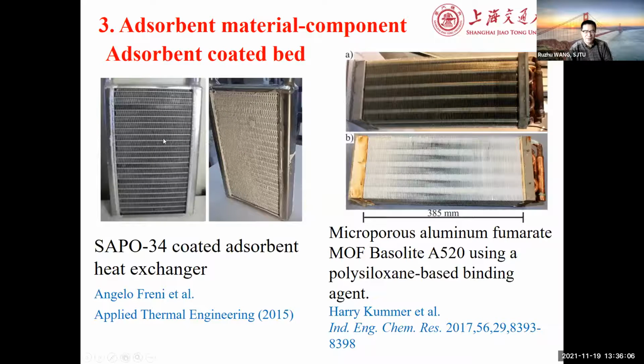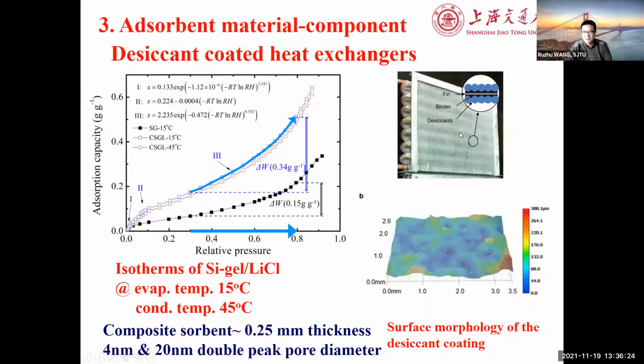And also we developed some desiccant coated heat exchangers. So there's a heat exchanger coated with desiccant materials, even MOF materials. So this work was done by the German colleagues. They are using MOF material coated there. And we coated desiccant with silica gel and composite lithium chloride. So this composite is used.